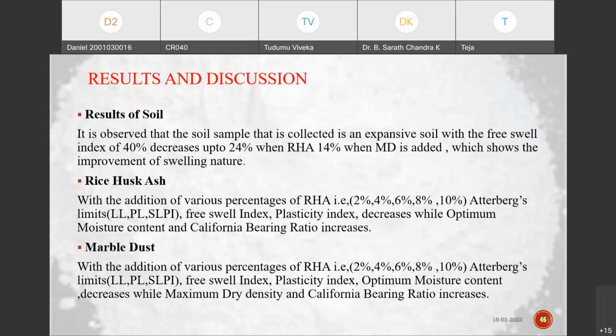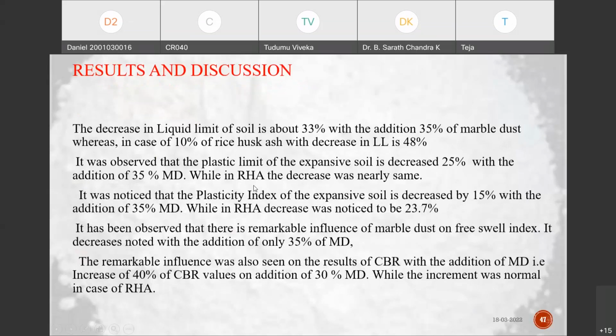In marble dust, maximum dry density and California bearing ratio increase. And we can see different results. There is a decrease in the liquid limit of soil of about 33% with addition of 35% of marble dust, whereas in the case of 10% of rice husk ash, the decrease in liquid limit is 48%. It was noted that the plasticity index of the expansive soil is decreased by 15% with the addition of 35% of marble dust, while with RHA the decrease was noted to be 23.7%. So we can see the results, which show the improvement of the soil when the additives are added.